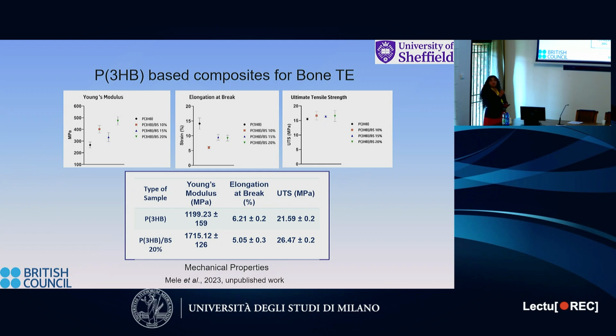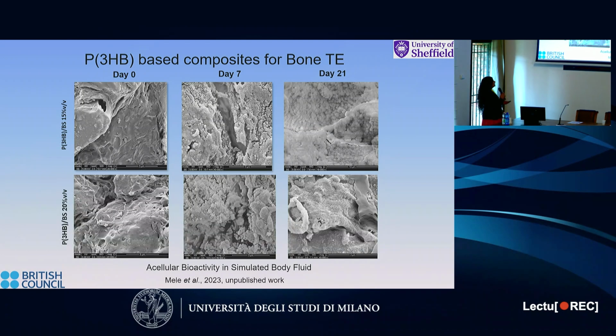And of course, then we look at the mechanical properties. A composite's mechanical property is perhaps the most important property, and we got a nice high Young's modulus value with the addition of 20% borosilicate glass. It gave us a higher Young's modulus, a similar elongation at break, and an increased ultimate tensile strength as well. This is exactly why we wanted the composite.